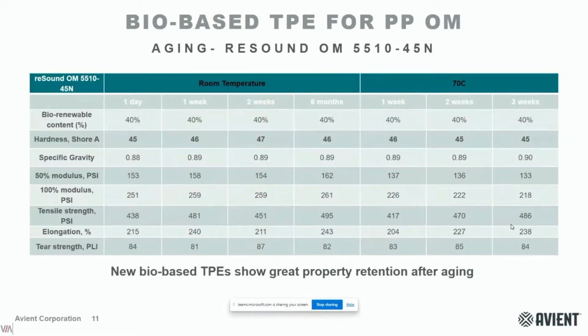We also made some tests at room temperature and also at 70 degrees Celsius related to aging of the materials. After seeing the results, if you look into the values of the specific gravity, the modulus, the tensile strength, elongation, and the tear strength, the values are in line from the first day to after 6 months. That means that we achieve a great property retention after this aging test. That means that the performance you can achieve initially will withstand the weeks and the aging, with proper property retention.